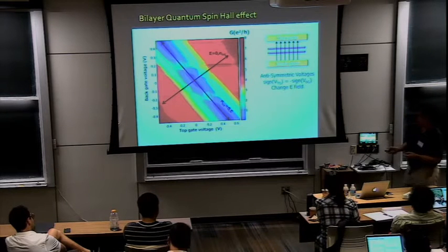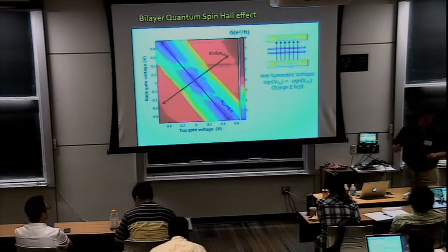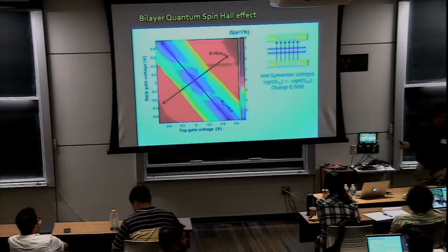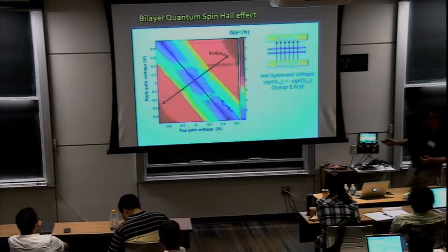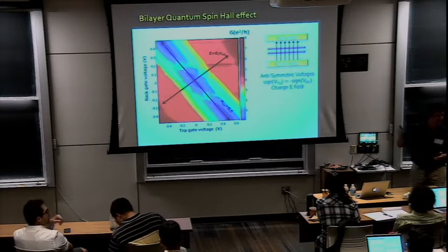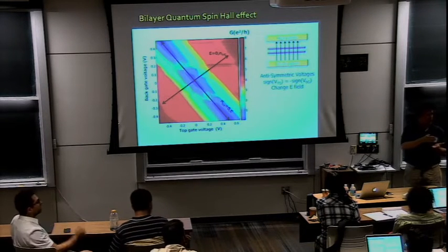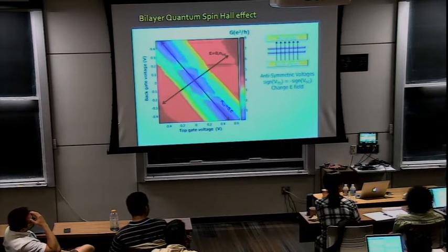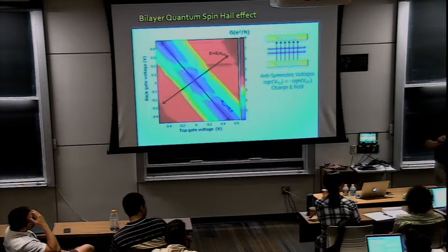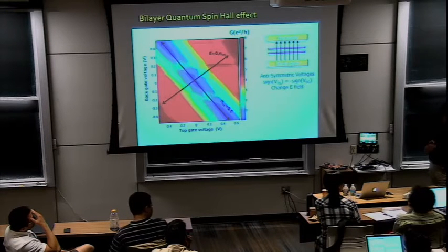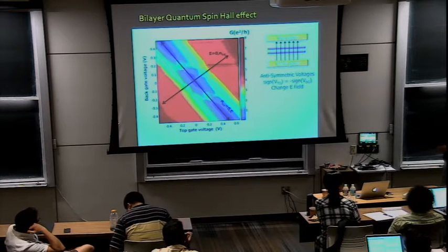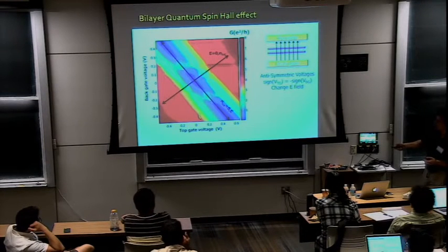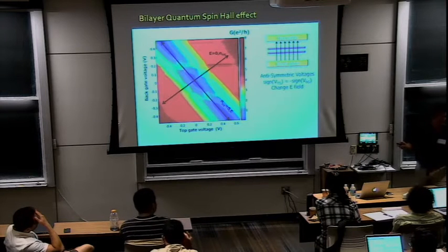The zero of the voltage is literally the zero of my apparatus. I have an apparatus connected to my samples and it has a 0, okay? Now, often, for example, in the data that I showed yesterday, 0 did not correspond to charge neutrality. That means that graphene has some impurities that donate some charge, and therefore I have to dial my voltage a little bit to offset those charges which are already present in the graphene. In this case, for this particular sample, there's a little bit of an offset here and a little bit of an offset here, so that cross is not exactly at 0, 0.